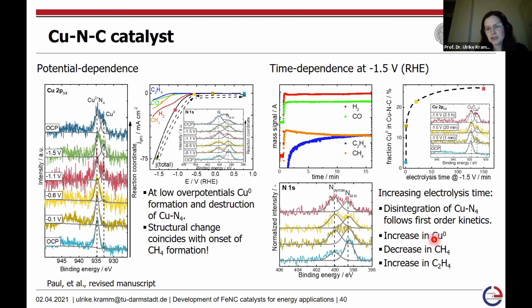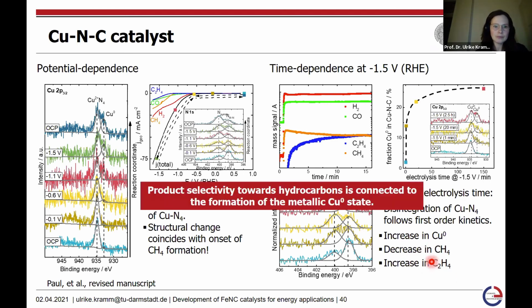First of all, we form the methane, but then over time, the methane formation decreases and we get even an increase in the formation of ethylene for the catalyst material. So that means the product selectivity towards the hydrocarbon formation seems to be strongly connected with the formation of the metallic Cu0 state, which is irreversible, as we were able to show by this scanning back approach.